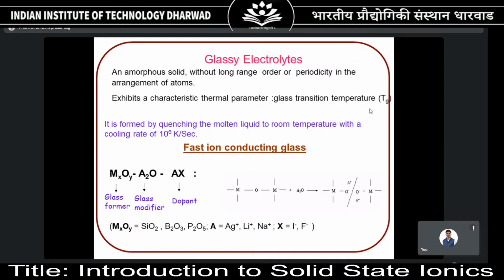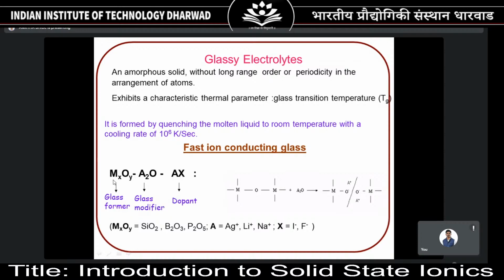And any glass that you have will show a characteristic thermal parameter called glass transition temperature. Let us look at one of the classic ionic conductors, glassy ionic conductor. A glass is composed of two things. One is glass former. They are basically oxides of silica, boron, phosphorus pentoxide, sometimes the sulfides, phosphorus sulfides, and so forth. They are glass formers. They're like polymer, like a chained structure, and glass modifiers. Typically, A stands for, in the case of ionic conductors, silver, lithium, sodium, and so forth. They're all the glass modifiers. So glass former and glass modifier.